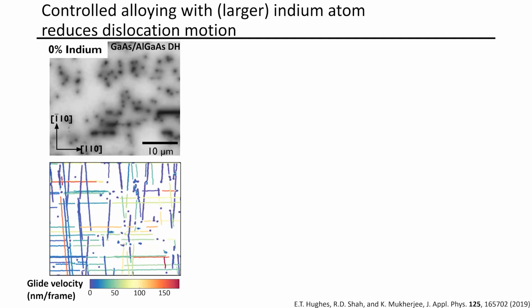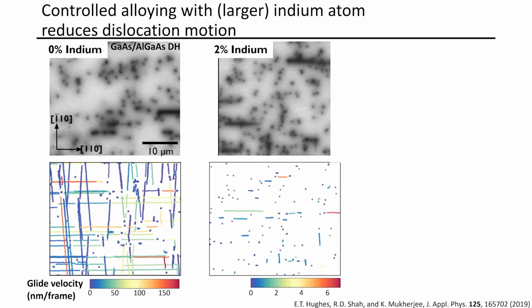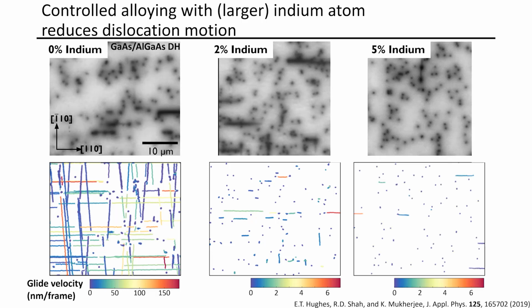We saw this a lot, and we've been thinking about what exactly we can do with this. Here's a light emission map of the same process. Right, so this is gallium arsenide. It's a very important semiconductor. You're just seeing the light emission from gallium arsenide. Little dots, the dots are moving around at room temperature. We discovered by chance that when you start alloying gallium arsenide with small percentages of a slightly bigger atom, we can actually remarkably harden the lattice.